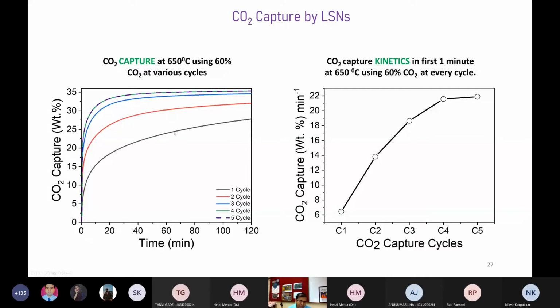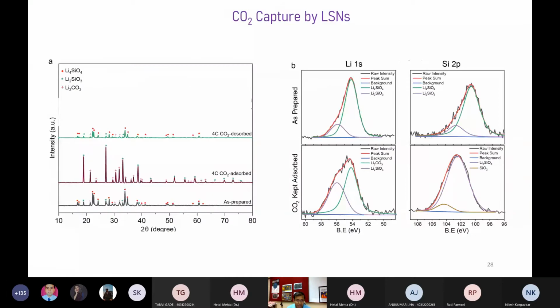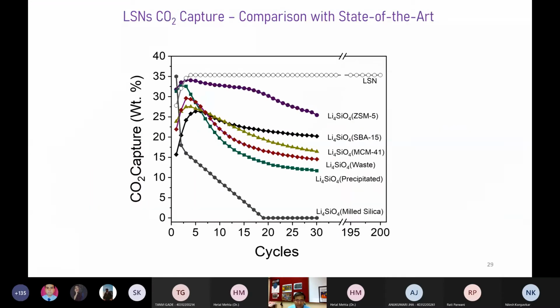And it's not only the capture capacity that is important, it's also kinetics, because gas is coming through something, and you want to really capture it as soon as the material sees the gas, sees the CO2. So that's the kinetics, right? The residence time of the gas on the sorbent will be very less, so you need to capture very fast. So you can see the kinetics of the CO2. It's like a first initial kinetic. So within a minute, it captures around 22% of the CO2, which is again a good number. And I will skip the more technical details to show some other examples.